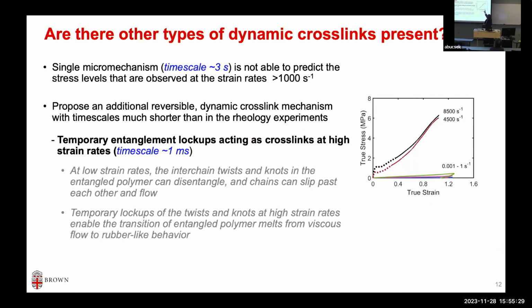That mechanism cannot explain this large jump at high rate. Really. So there has to be another dynamic reversible crosslink mechanism. And we propose that, and this is in our paper that we recently published. The second mechanism is temporary entanglement. So imagine these chains that also have a physical entanglement. If you're looking at a larger time scale, they are sliding past each other. But at a very short time scale, millisecond time scale, they actually act as junction points, as cross-linking.